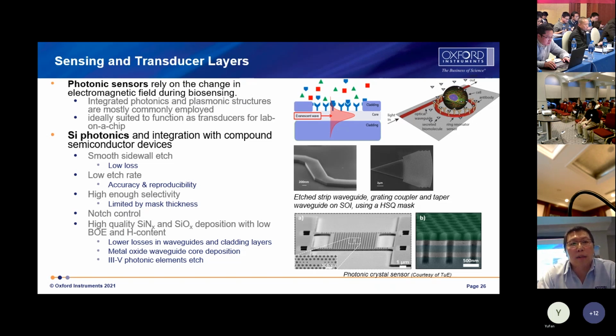State-of-the-art silicon waveguide fabrication combines e-beam or deep UV lithography and subsequent plasma etching processing to transfer the pattern into the SOI device layer. The top thickness is about 200 nanometer, and some shallow grating etching only 70 nanometer. The process requires smooth sidewalls for low propagation loss, low etching rate for accuracy control, and high enough selectivity, because that's limited by mask thickness, but also notch control at the silicon dioxide interface.